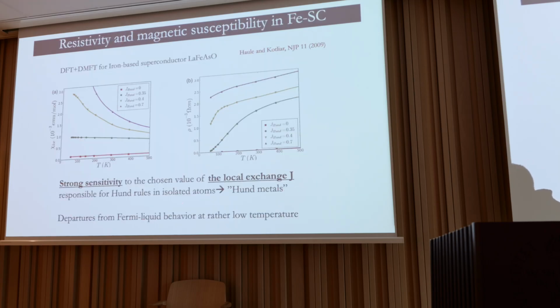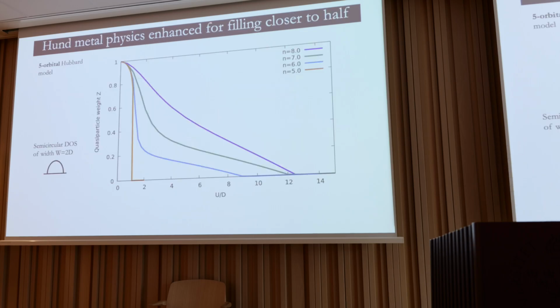Gabi, by the way, Gabi Kotliar did calculations for the iron-based superconductors very, very early on, and this was more of an evidence ab initio, in which he realized that Hund's coupling was really changing the quantities that you could compare with experiment. For instance, the local magnetic susceptibility or the resistivity were really shooting up when you would crank up Hund's coupling. So that's what brought attention to the Hund metallic phase, and he invented the name.